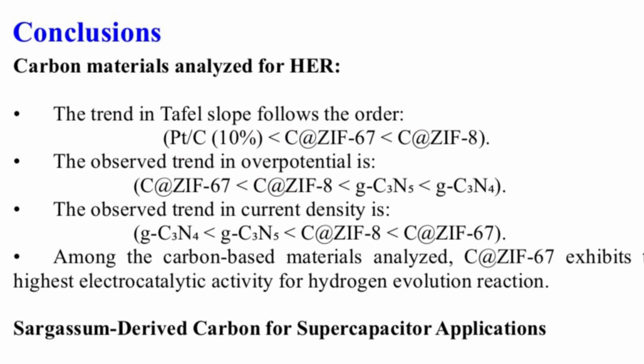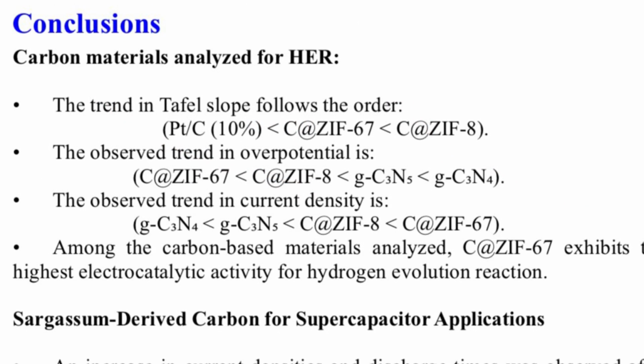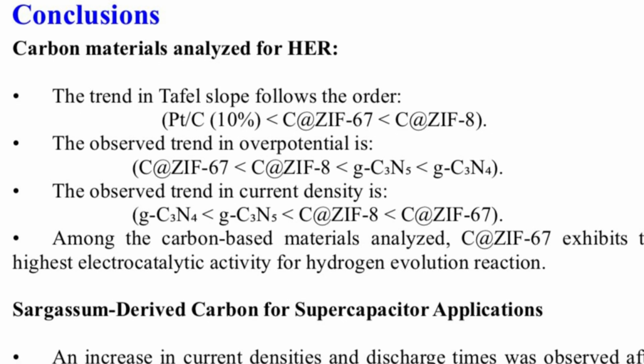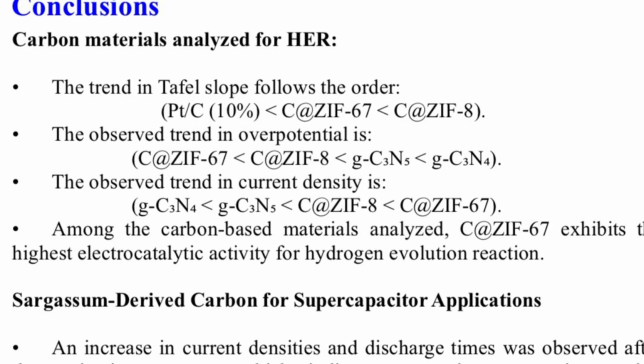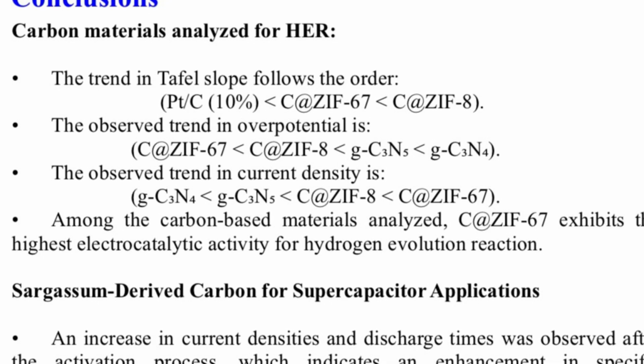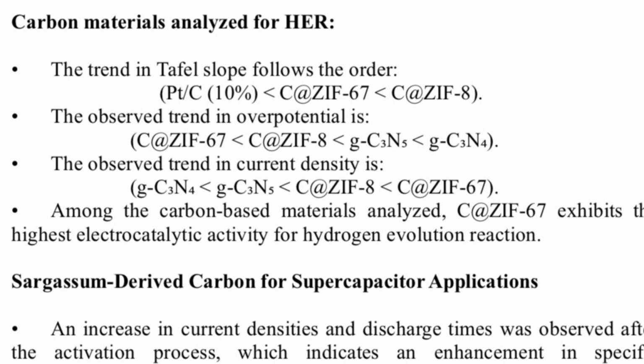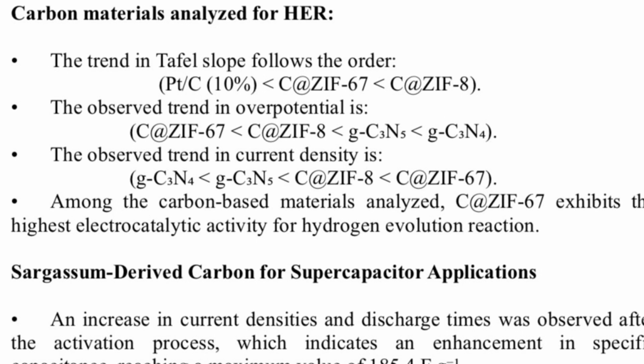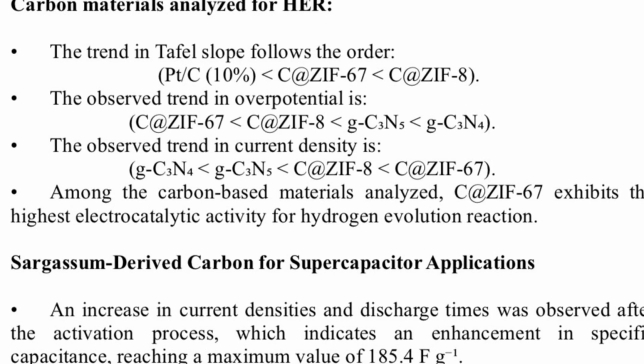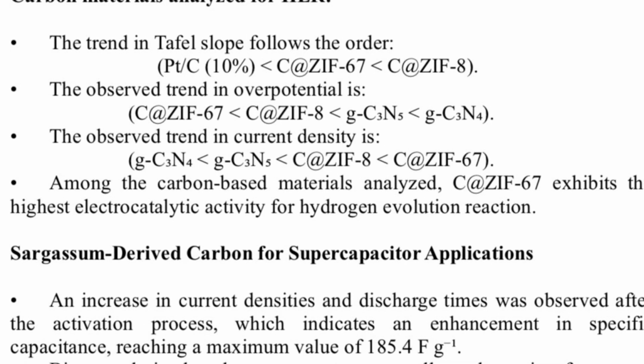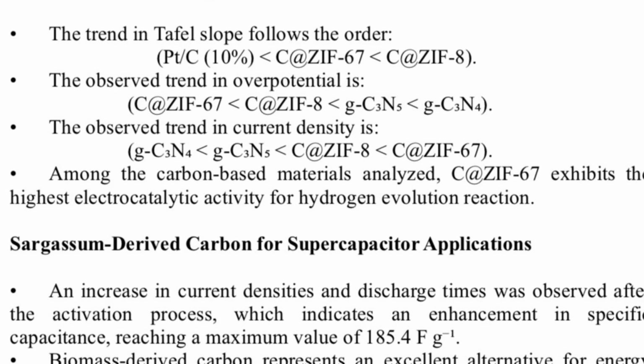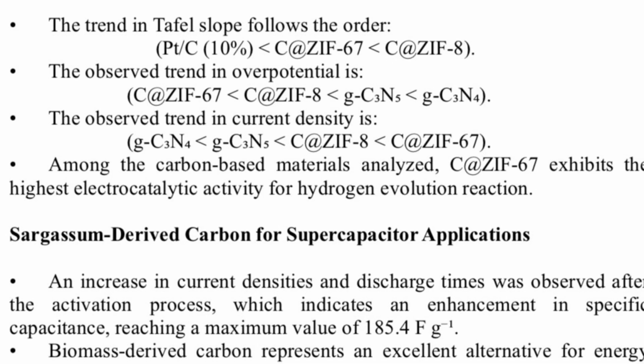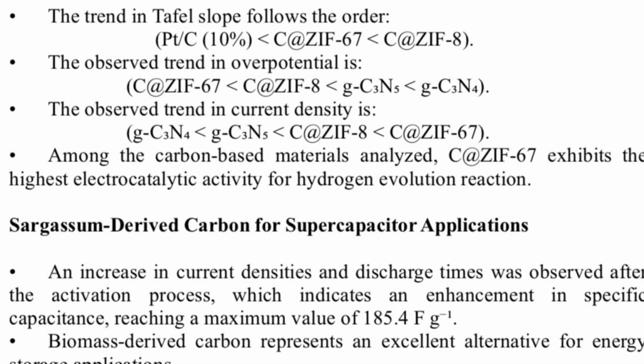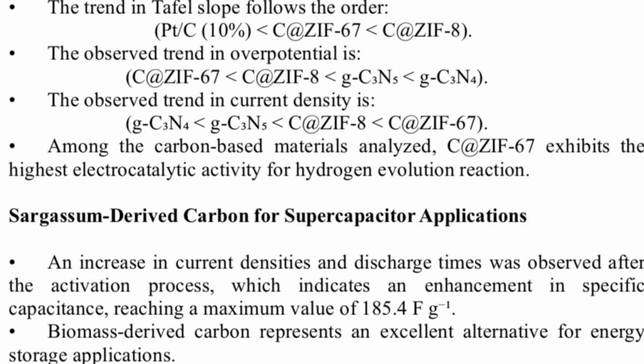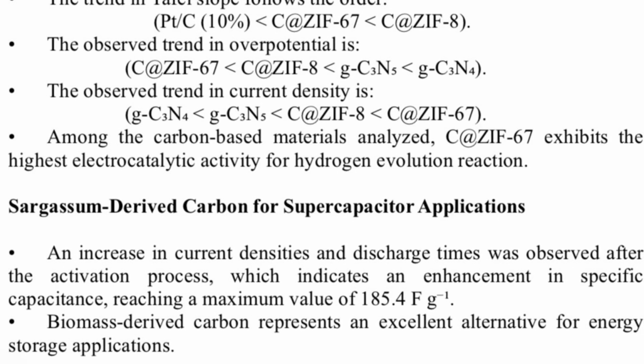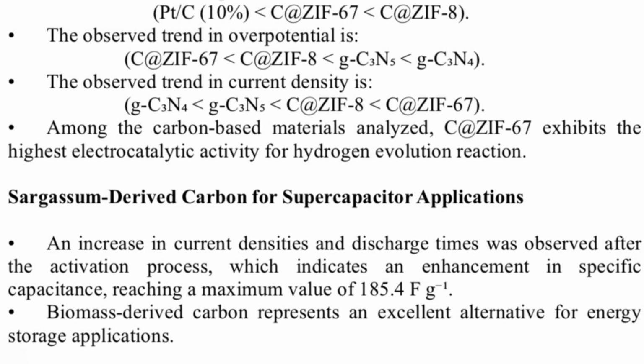Results show that among the 4 studied carbon materials for hydrogen evolution reaction, ZIF-67 requires relatively low overpotential and shows a promising Tafel slope, reflecting its highest electrocatalytic activity for HER. On the other hand, for the carbon derived from sargassum for supercapacitor applications, an increase in current densities and discharge times was observed after the activation process, which indicates an enhancement in specific capacitance, reaching a maximum value of 185.4 farad per gram.